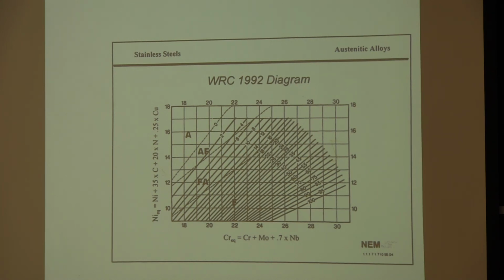And so in order to avoid cracking, like I said earlier, you want to really be in this FA type solidification range. And so as you figure out the chromium and nickel equivalents of the material that you're welding on, and you can also figure those out for the filler material that you're using, and then you can figure out where you're going to end up on this and whether you're going to be susceptible to cracking or not.